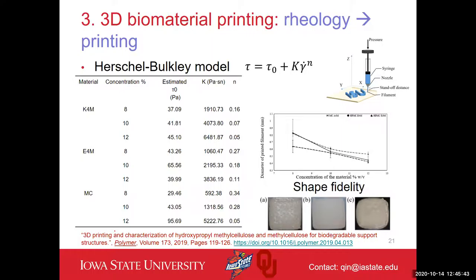The evaluation criterion we selected is the shape fidelity. So after printing, will the part be able to maintain its geometry, maintain its 3D shape? That is the shape fidelity concept we are talking about. There is high water content in the liquid-phase cellulose material, so during the printing there will always be water evaporation. If there is too much water evaporation, the printed part itself cannot hold its geometry.